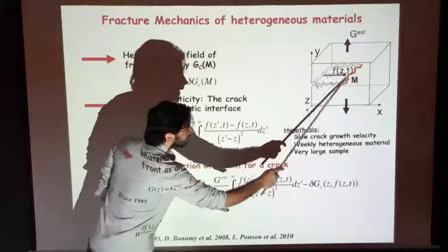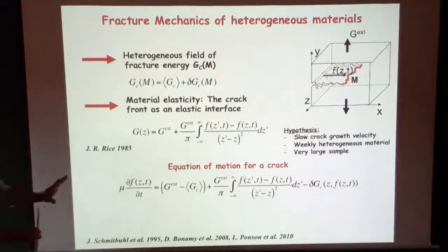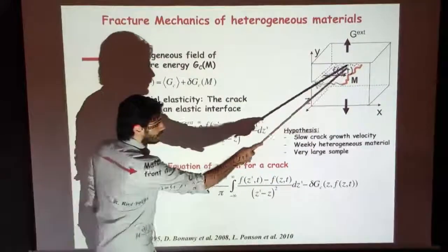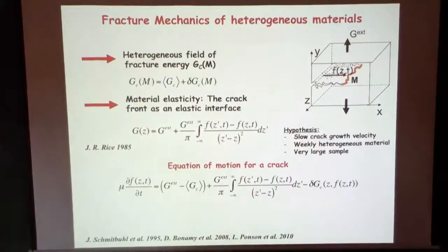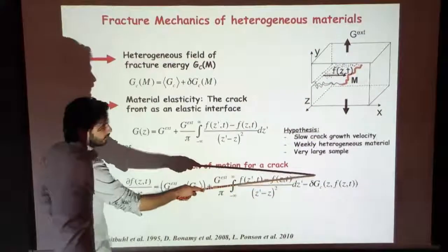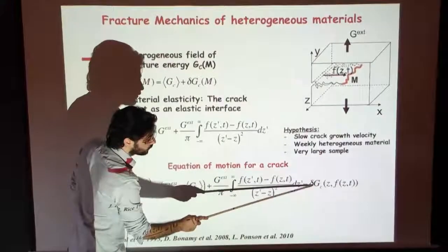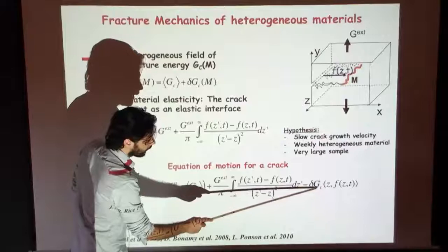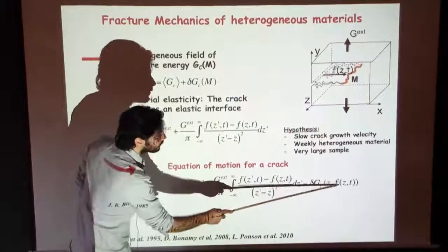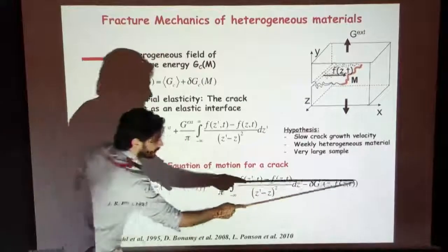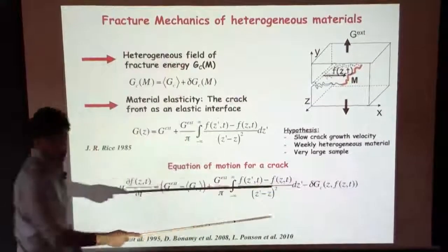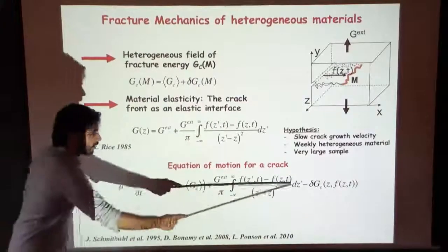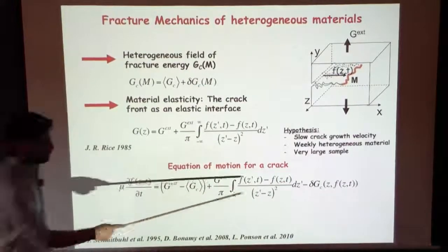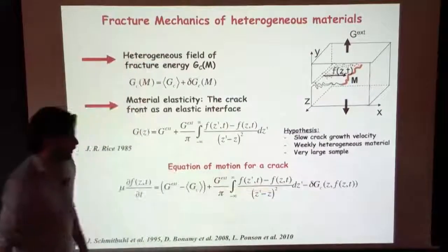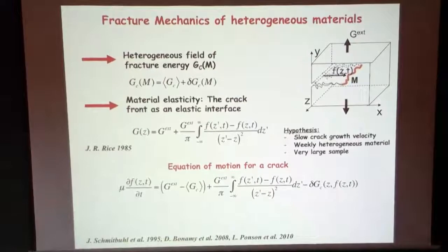I didn't mention the in-plane perturbation of the front. I assume very small out-of-plane perturbation, weakly heterogeneous material, so I neglect the effect of out-of-plane excursion of the front on the stress field. Then you apply your local fracture energy on the front you are considering, and the complexity in your equation arises from this nonlinearity. If you didn't have that, you would have a linear equation you can solve in f, but because of the presence of your unknown f inside the heterogeneous term, you get into big trouble.